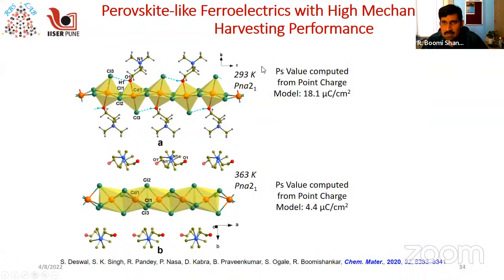Okay, so we also measured the polarization using PE loop analysis, which gives a polarization value of 18.1 microcoulombs per centimeter squared, or 17.5. We can also calculate the polarization using a point charge model. In the coordinated state, the calculated polarization is 18 microcoulombs, whereas in the uncoordinated state, the calculated polarization is only 4.4 microcoulombs, which tells you that the modified ferroelectric structure designed by our cations is actually giving rise to a long range polar order.